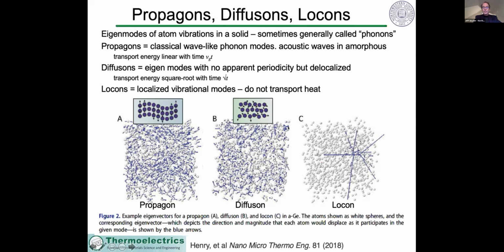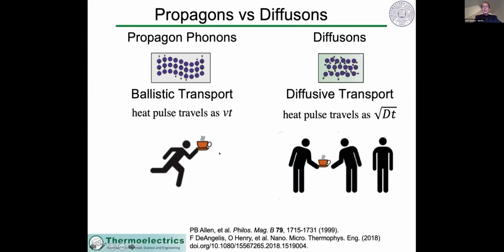scattered throughout the material. So the way we like to think about it is that phonons, or now more specifically propagons, travel ballistically. A heat pulse travels proportional to time using a velocity, whereas diffusons transport their heat diffusively by handing the energy over from one mode to the other, as opposed to traveling with a velocity. And so then the heat ends up traveling like diffusion, through square root of time.